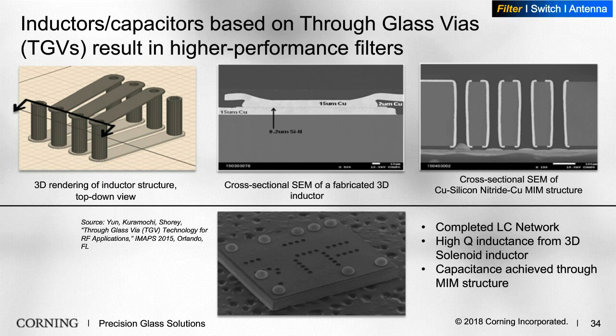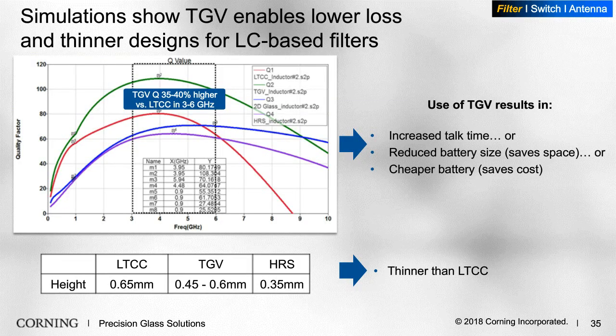And what we're seeing is that a true 3D approach and an element which has the lowest losses, so the best conductivity and the lowest capacitive losses, results in the highest Q. So Q is the measure of that quantity, and we see that over the incumbent technologies, things like LTCC and high resistivity silicon, over the sub-6 gigahertz frequencies, the true glass-based or true glass via-based elements hold the highest performance. So that would lead to thinner, smaller implementations and certainly lowest loss or lowest current drain.